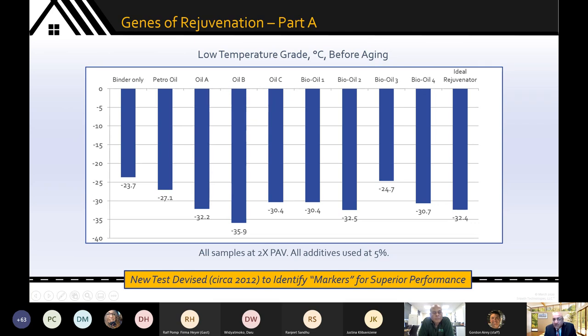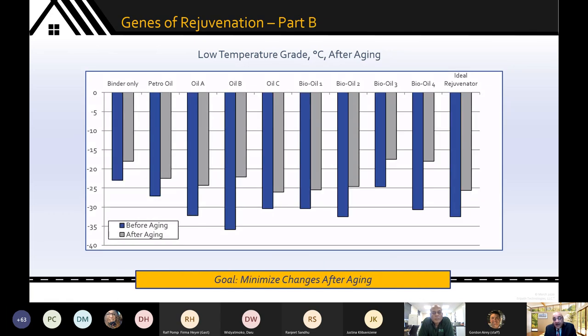Until you do one more step, you take each one of these materials and age it again to look at what would be the performance if this material was put down in a roadway 5 or 7 years out. And that's this graph. The blue lines are from the previous chart. The gray lines are after aging of each of these materials, the second aging, if you will. What you can see is that this material shows a very high degree of change. The delta is quite high.